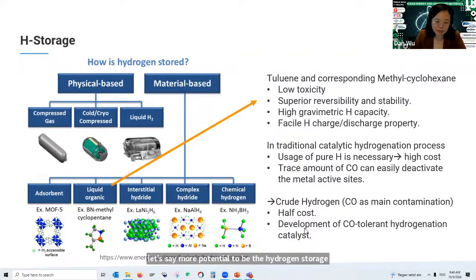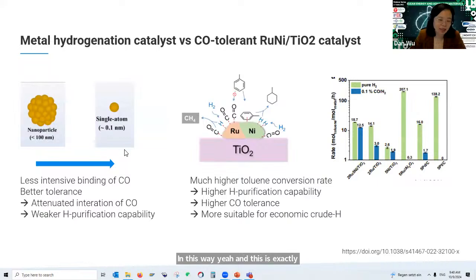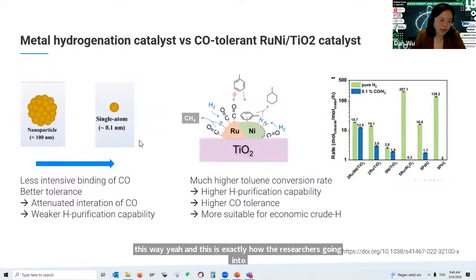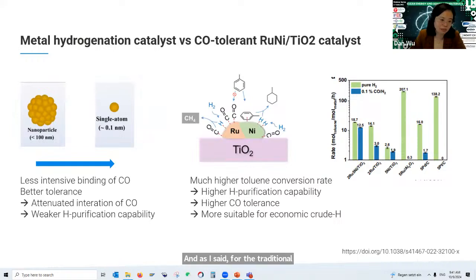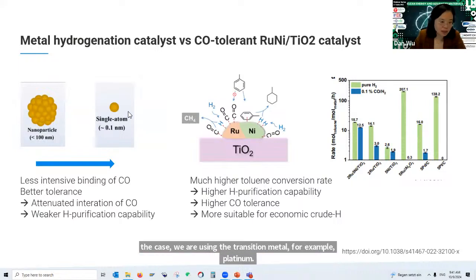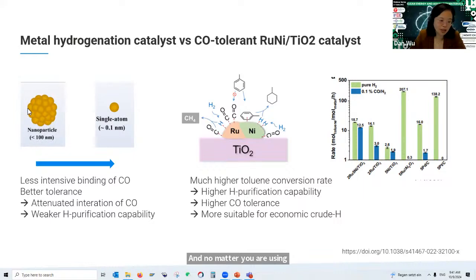But then that means you have to develop a CO-tolerant hydrogenation catalyst in this way. Yeah, and this is exactly how the research is going. As I said, for the traditional catalyst, we often use a transition metal, for example platinum. No matter whether you use single atoms or nanoparticle clusters, we can fine-tune the binding of the CO to the metal particles to get better tolerance of the CO.